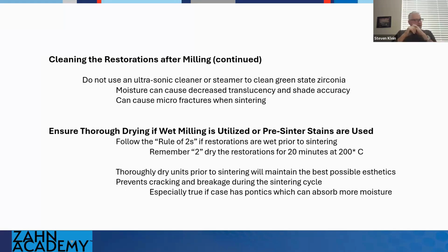Cleaning restorations after milling, you do not want to use an ultrasonic cleaner or a steamer to do that. I've seen both done, not ideal. Moisture can definitely cause a decrease in the translucency, given it's almost 100%, and the shade accuracy will also diminish. The other aspect too is, like with a steamer, you can induce microfractures into the material much too easily with using either one of those techniques.